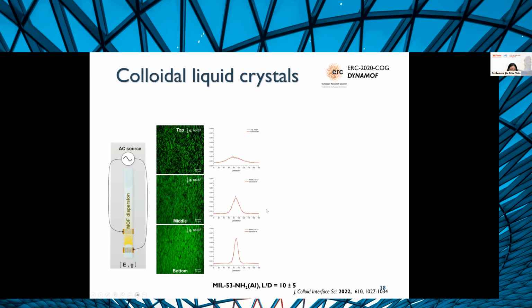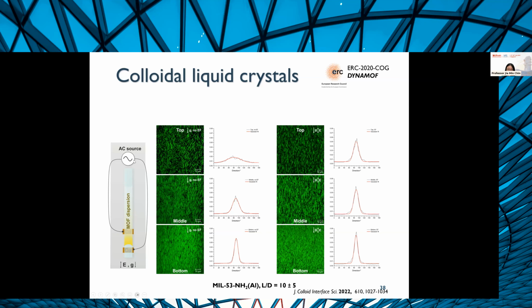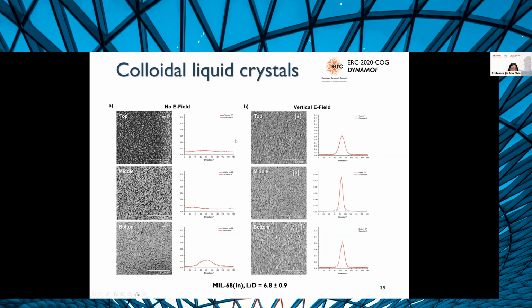But then as you go further down and increase packing density, you end up indeed having a very oriented assembly. However, if you move to a different setup where you actually do apply the electric field, then you see that regardless of the packing density, throughout the whole capillary, the MOFs are very nicely oriented, and you get closely packed crystals with this orientation. We then see that also with MIL-68, with a lower aspect ratio, we do get some kind of preferential orientation when you have high packing density in gravity without an electric field, but it's not perfect. And here you really don't see much directional preference at all.